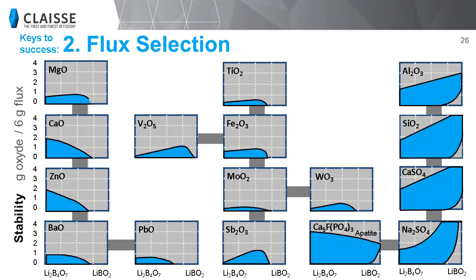However, if you are looking for a universal solution for many different samples, then a 50-50 mixture of lithium tetraborate and lithium metaborate is probably the best option. However, you may have to decrease the amount of sample diluted per amount of flux. It means that if you go for something universal, you will probably have to reduce the sample-flux ratio.